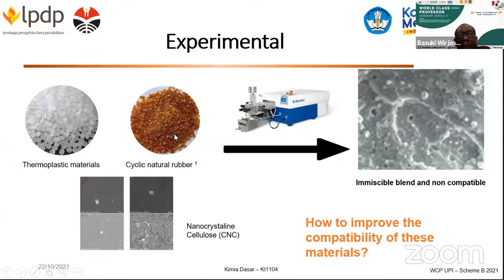So we can easily blend it using an internal mixer, for example, at melt temperature. But when we blend polypropylene and cyclic rubber directly, the blend is not compatible, because they have different properties. The thermoplastic is very hydrophobic, and the cyclic rubber is more semi-polar. So this is the main thing: how to improve the compatibility of these materials.